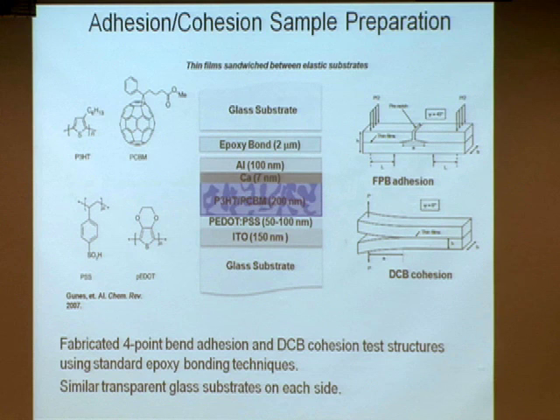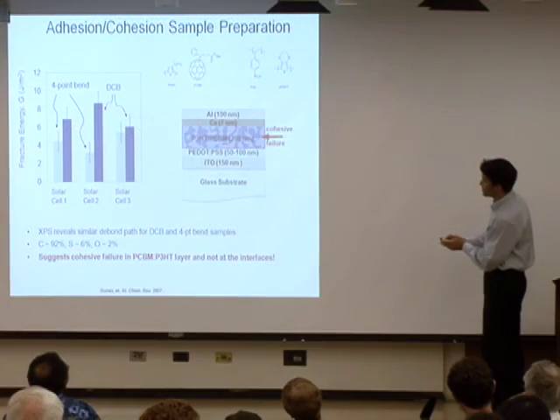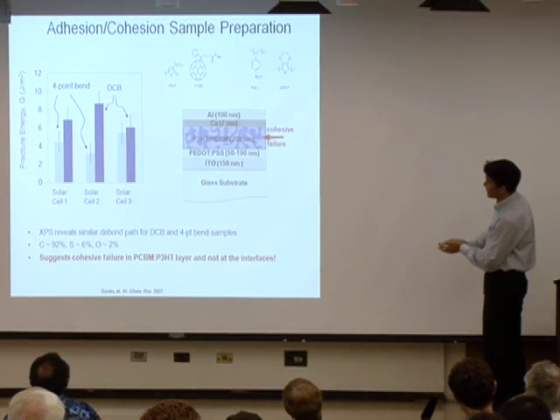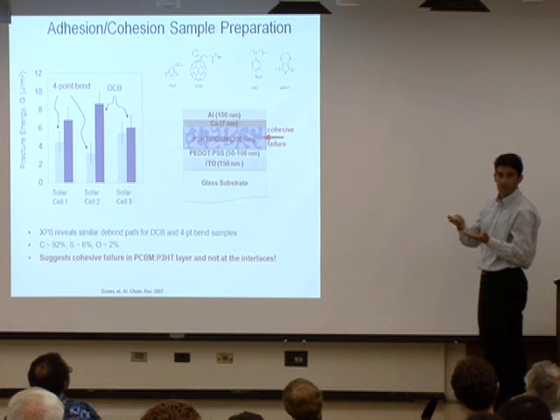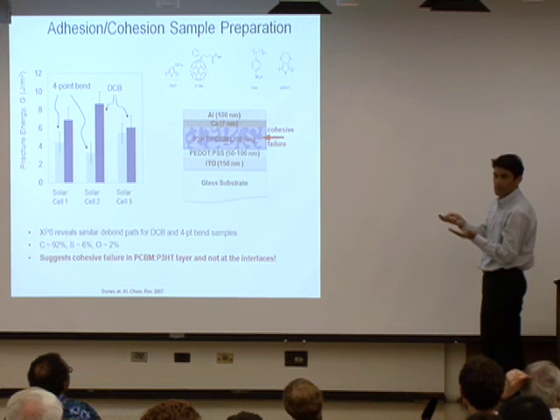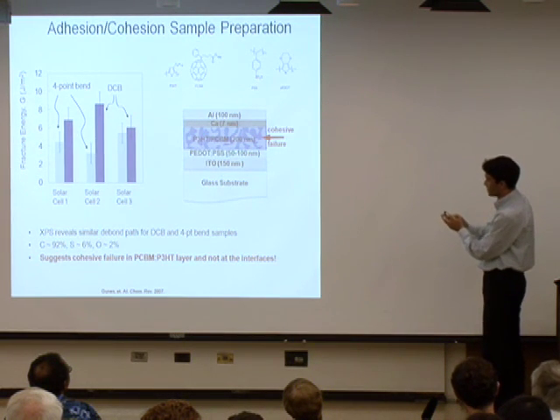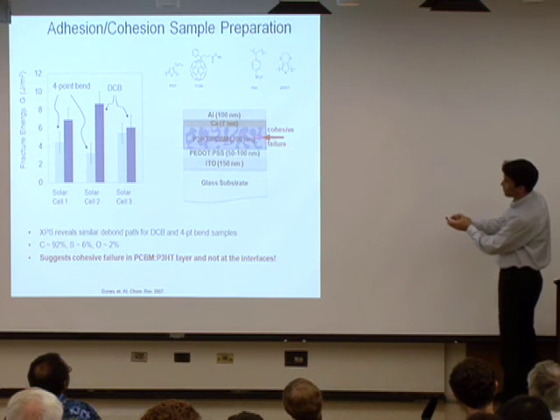And so surprisingly, you would think that the failure would occur at an interface. And this is traditionally what happens, but he found that in fact the failure is happening within the active layer of the device. And so he can analyze this just by reverse engineering, looking at the surface and seeing what's there. So this was an interesting discovery, and this will also help us in the future, maybe we need to think about other types of material combinations to make it so that the failure is not occurring in the active layer.